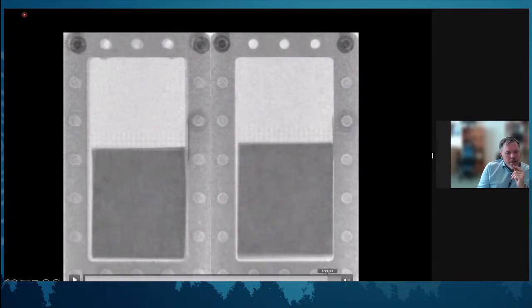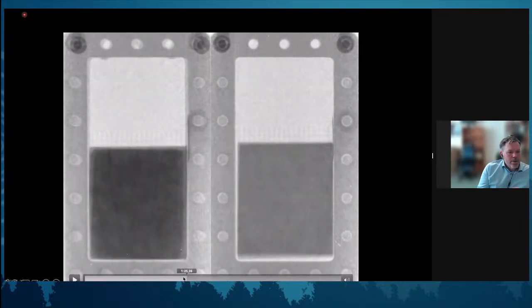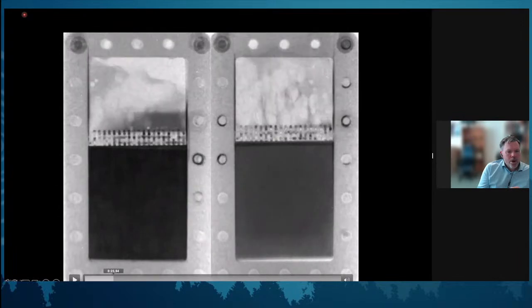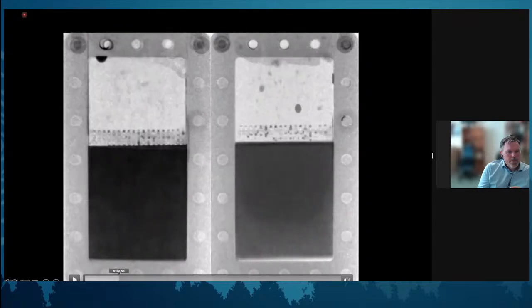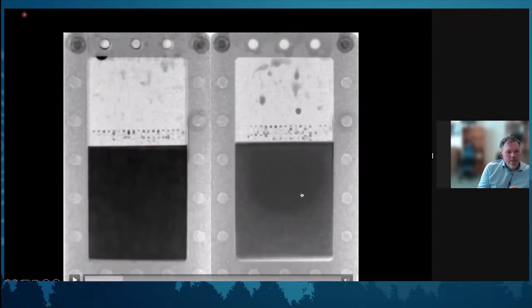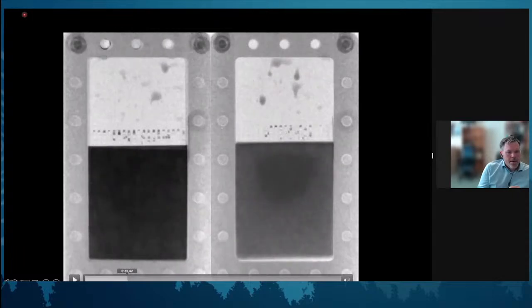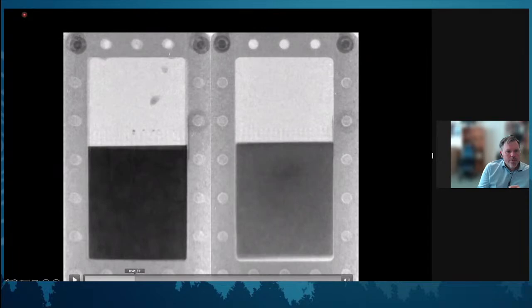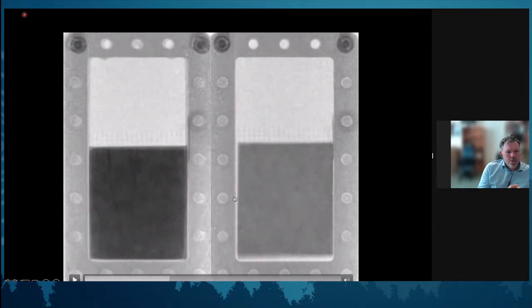And at the end, we can only see the cellulose because it's hydrogen there. It's the same amount of cellulose, so we can actually see also a little bit of the structure of the material. Just to point out something that happens in the end when drying. So please have a look at the right one. Look at the edge when we're drying now. So we have water still here. This is dry. And then now all water is gone. And the last thing that happens is that this piece of cellulose actually also shrinks. So we can study the shrinkage of the material.